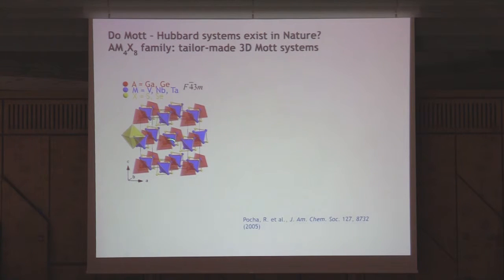So it looks awfully complicated, but it's quite simple. You have to forget about the gallium or the germanium, which is the red octahedra here. Forget about them. Here you have some, also in yellow, the sulfur or selenium, that you can also forget about. And the only thing to retain is just the blue octahedra, which are made of a transition metal oxide, which could be vanadium, niobium, tantalum, molybdenum, a variety. And all these families are all Mott insulators. Many of them do not order in any way, do not have any structural transition, so you can go to very, very low temperatures.